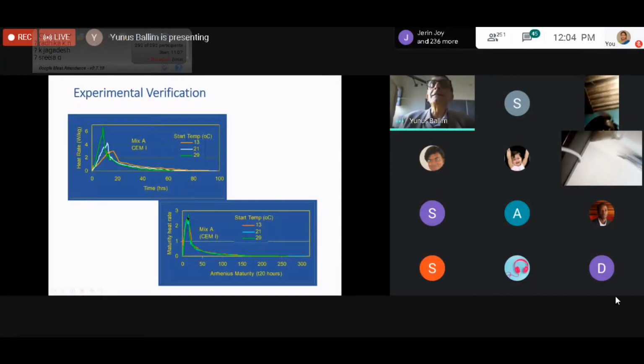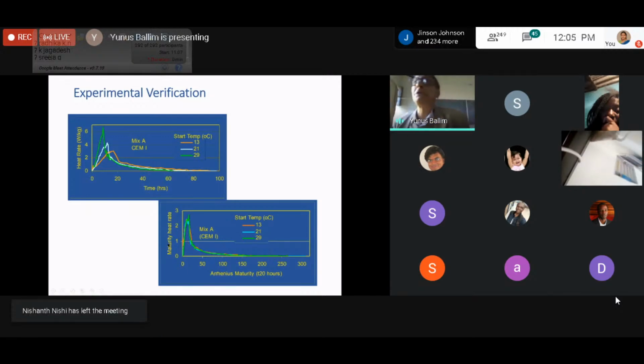You can see that this curve sort of lies around the level of this one, which started at 21 degrees, because we're bringing everything to T20 hours. And so what we now have is an ability to produce a normalized heat rate function, which then allows us to start thinking about how we solve the Fourier equation.